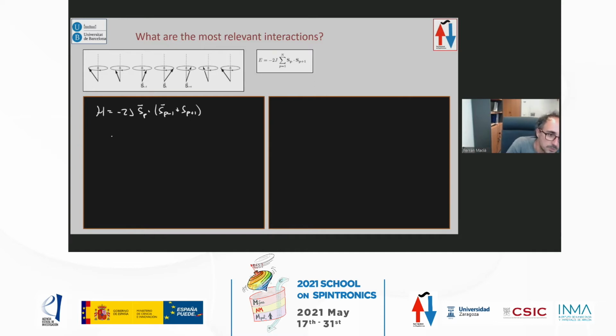Another thing we know, as we said before, is that the magnetic moment associated to a spin is g mu_B S_p, where g is 2 for an electronic spin, right? So now we can write that down and say that this is mu, the magnetic moment, and we have a constant, which is 2J over g mu_B, times dot, sorry, S_(p-1) plus S_(p+1).